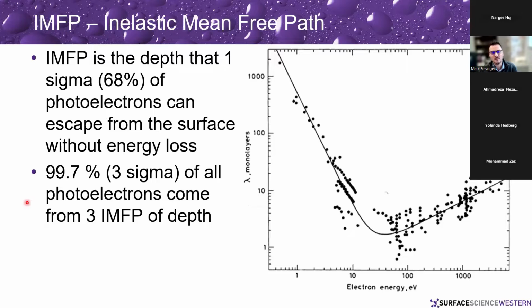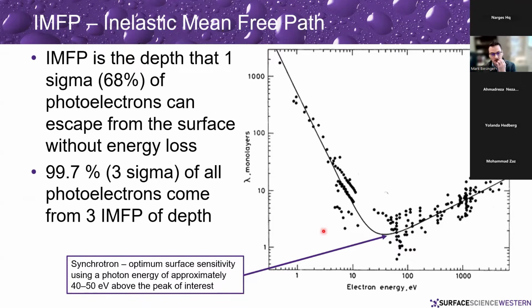And the way that works is if we look at what's called the inelastic mean free path. So this is the path that 1 sigma, or 68%, of photoelectrons can escape from the surface without energy loss. If you have 3 sigma, that captures about 99.7% of all photoelectrons that come from that depth. And if you have a tunable source, you're trying to get your synchrotron tuned to be about 40 to 50 eV above this curve here. And so that will be your maximum surface sensitivity available by XPS.